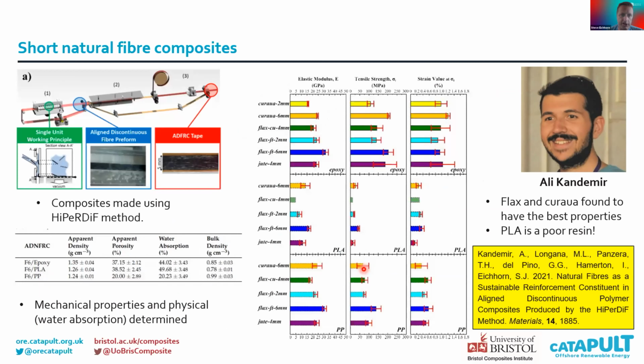And then he's moved on to looking at some short natural fibre composites, and I'm sure Ian Hamerton is going to talk about this later on, so I won't go into too much detail. This is a HiPerDiF method where we take short fibres and make continuous composite tapes, and the properties of these tapes are really quite impressive. He's been able to take all of these fibres and mix them with different resins as well, so epoxy, PLA, and polypropylene here. We found that PLA is a pretty poor resin, but flax and curaua have the best properties for use in the composites. So we're moving on now to look at other composite systems and get a better understanding of how natural fibres can compete or maybe even combine with glass and or carbon fibres as well.